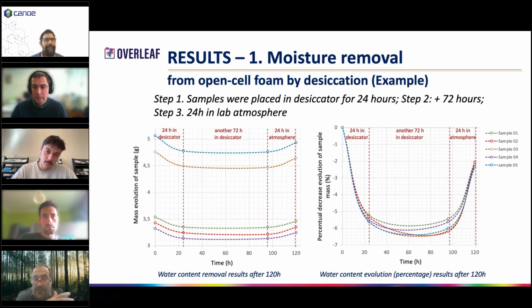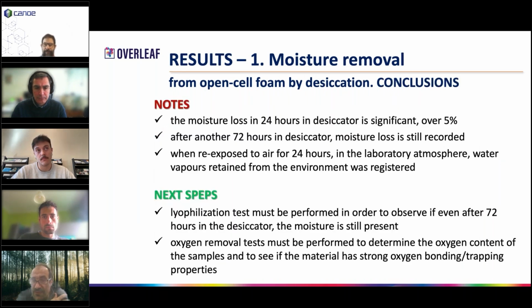In these two graphs, we present water content evolution after 120 hours as mass, and also as a percentage of mass. From the graph, you can see that the vast majority of the water is eliminated in 24 hours in the desiccator, and after 72 hours, if we keep the samples still in a desiccator, the variation in mass and percentage is not very significant. It means 24 hours can be enough to take the water out, although if the samples are put back into the lab atmosphere, they will catch back the same percentage of water, almost to the same levels.